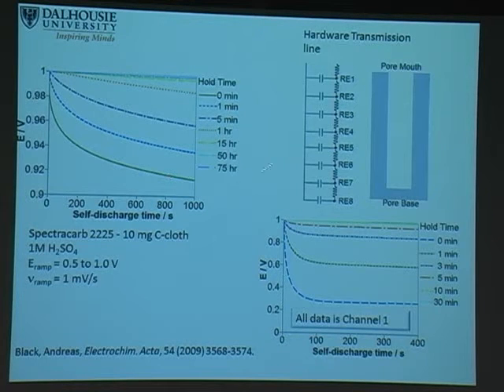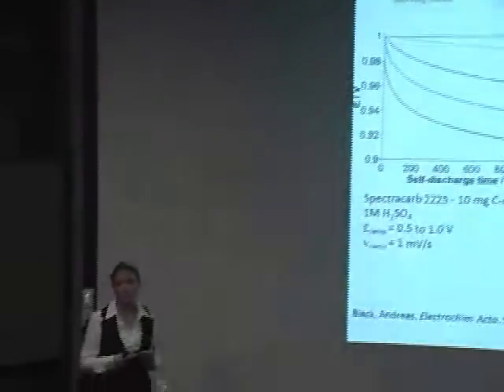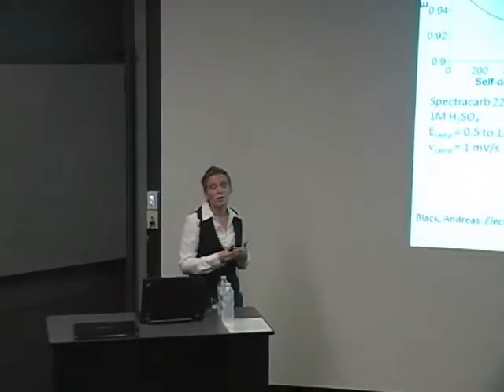Those of you who are quick are going to notice that we have very, very long times here. So we're holding these potentials for 75 hours. We would expect those lengths of times would also be influencing Faradaic reactions. And so again, this didn't allow us to completely separate these processes out, because we would be reacting away whatever might be causing the Faradaic reaction.